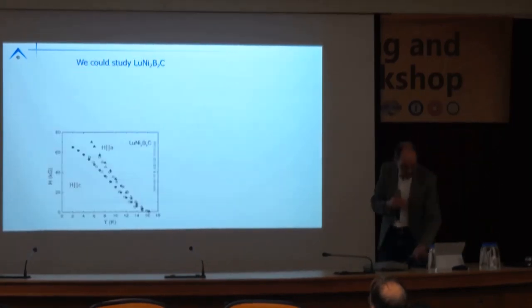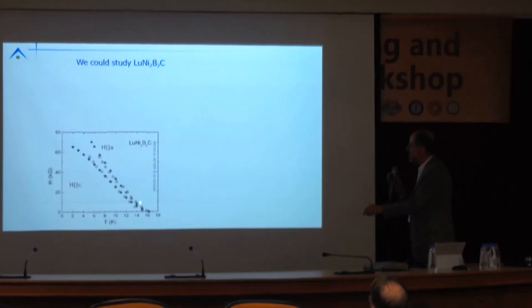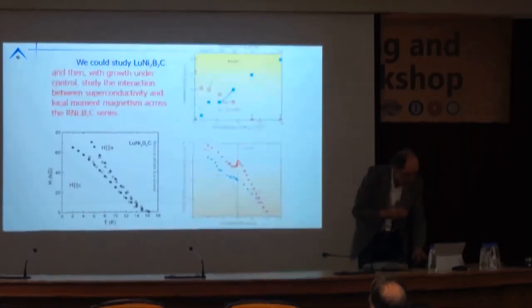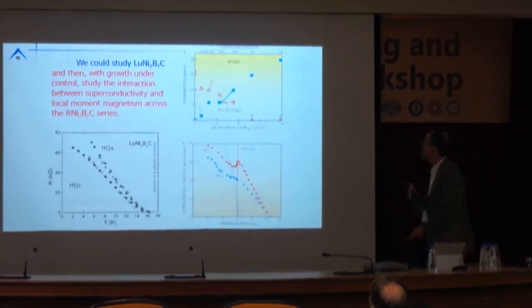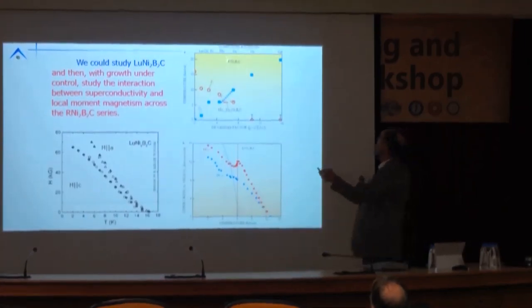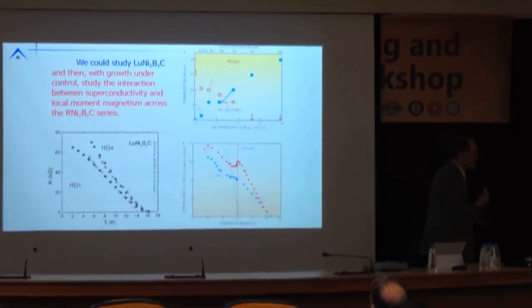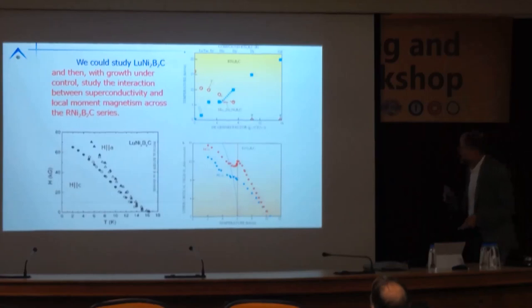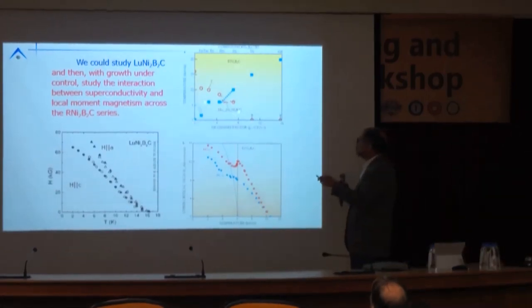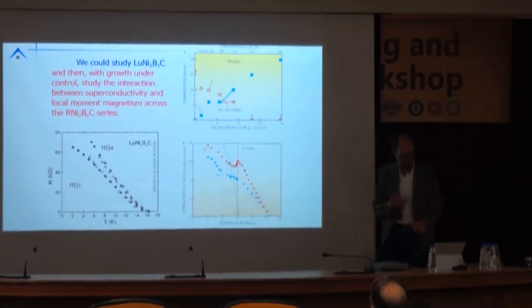Okay? Now, this material has a TC of about 17. It has actually a rather remarkably low HC2. It has a minor anisotropy. That's really nice. On the other hand, what we were able to do is, having grown lutetium nickel borocarbide, we can look at the other rare earth nickel borocarbides, and for thulium, erbium, holmium, and dysprosium, we have not only superconductivity, but we have antiferromagnetic order and the interaction and competition between them. Okay?